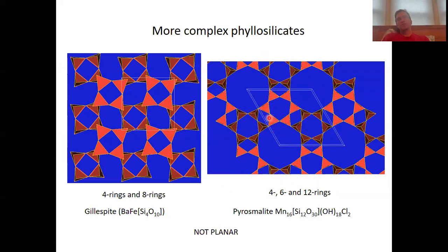Okay, so these tetrahedra here point down, but these six-membered rings then have adjacent six-membered rings in which all the tetrahedra point up. Okay, so one six-membered ring is shown here, then another one is shown here, and another one is shown here. Okay, and each six-membered ring in which the tetrahedra point up is surrounded by three six-membered rings in which the tetrahedra point down.